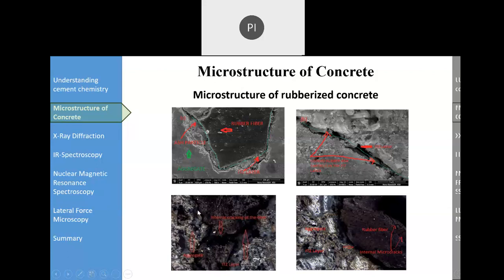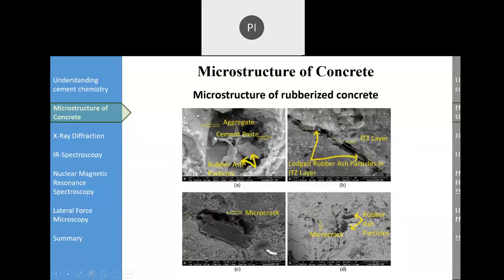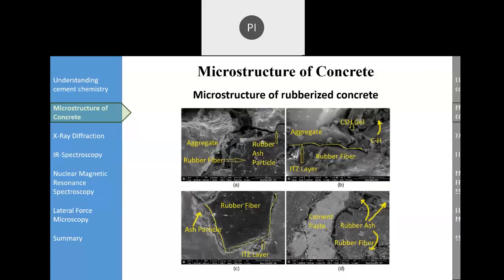The fiber is cracking internally, and these are internal micro cracks on the rubber fiber. So again, here you can see the aggregate, this is the cement paste, and these are the rubber ash particles which are lodged between them, in the ITZ, and micro cracks in the rubber fiber. Again, what do micro cracks mean? They mean a lot. If the cracks were not initially there and the cracks have developed later on, during the impact, that means the rubber fibers cracked due to the impact, and that means a major part of the energy was absorbed by the rubber fibers. So different types of interpretations can be done by going through these microstructure images.